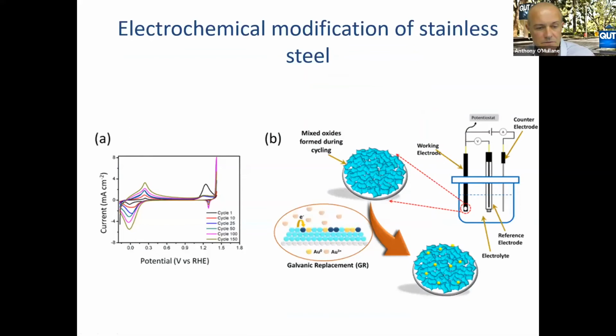So what we did was we did an electrochemical modification process. We take stainless steel, we put it into 6 molar KOH, which is a normal electrolyte used in alkaline water electrolysis. We can see here that if we cycle our potential, here we have a redox process associated with iron that's in the steel. Here we're getting a process due to nickel. And then we can see there's a rapid increase in current, which is due to our oxygen evolution reaction.